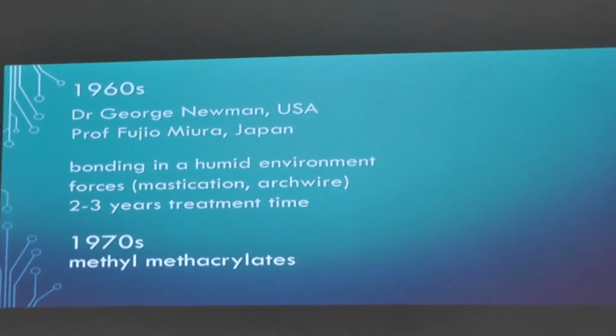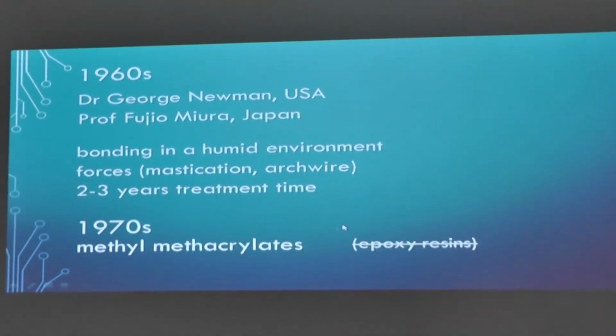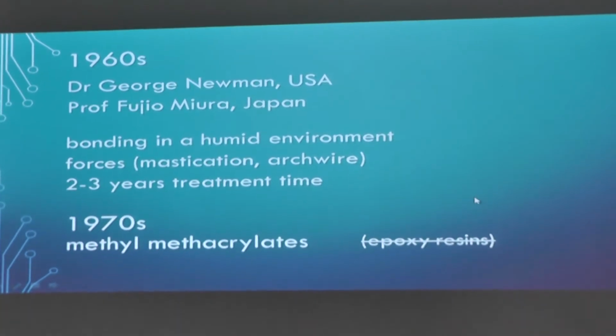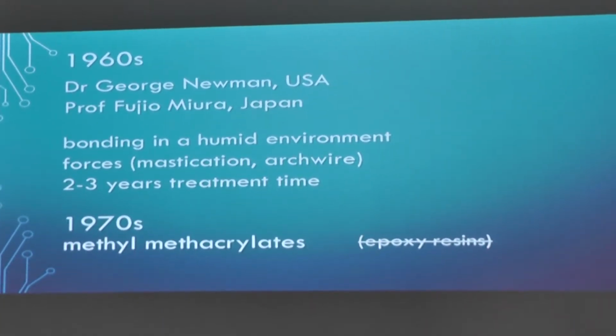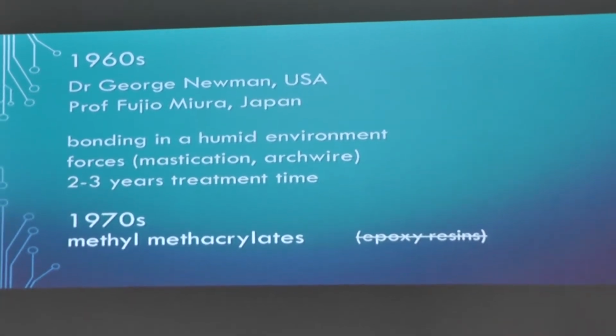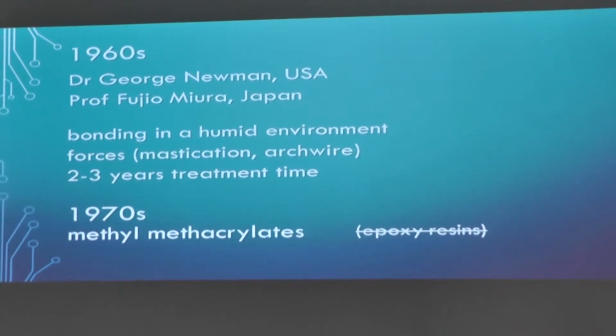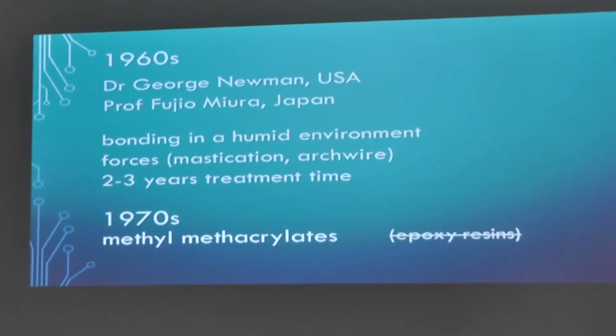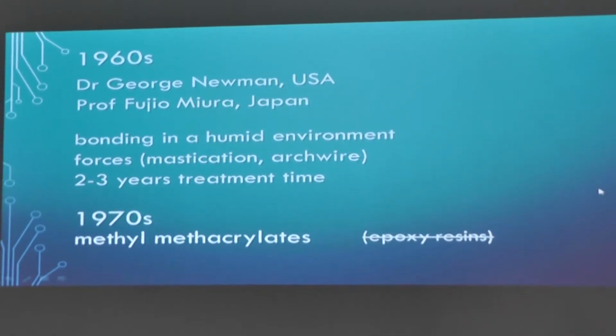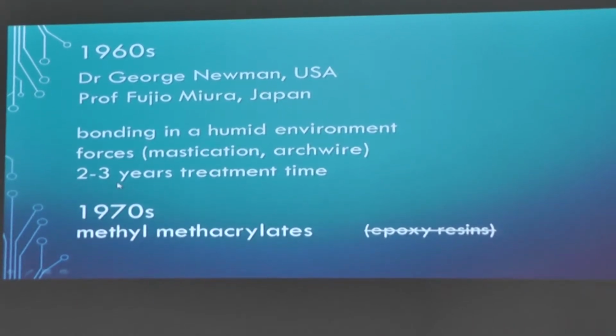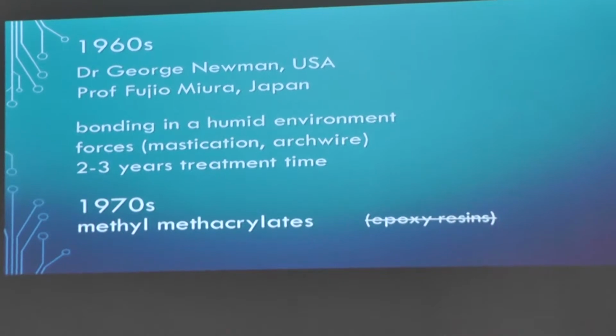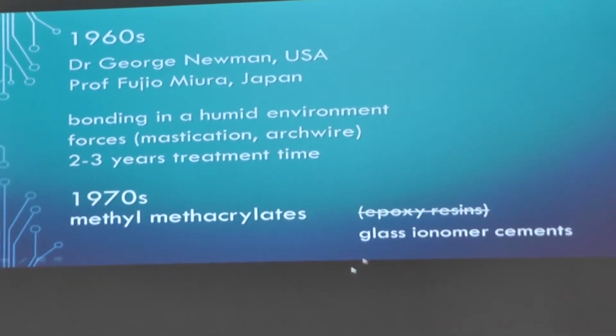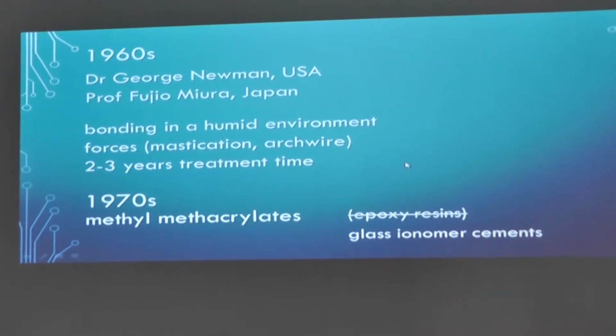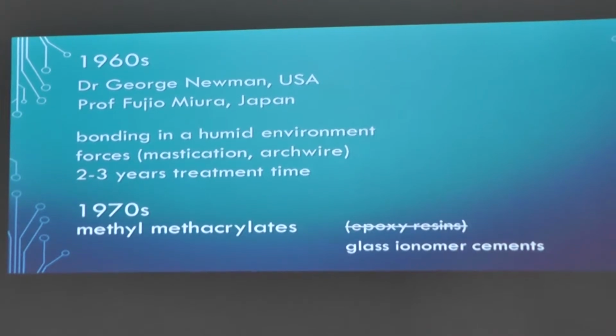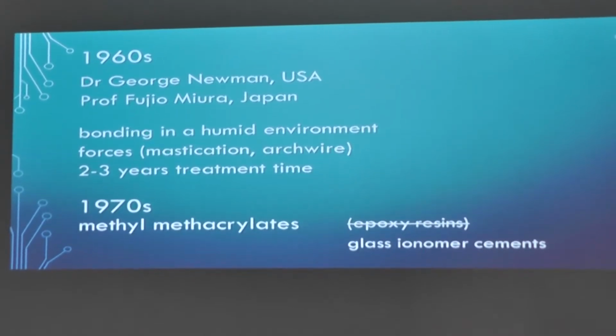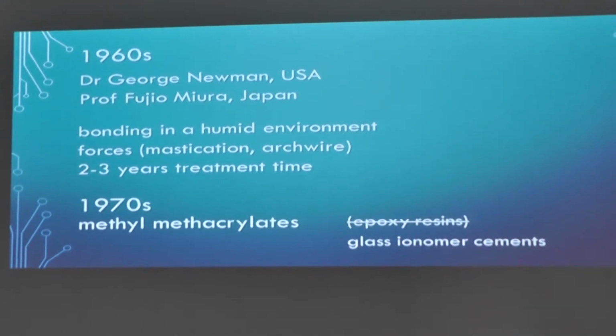materials were actually developed and used clinically. They consisted of methyl methacrylates, and also epoxy resins were experimented with, but they didn't have wide application because they have some toxicity, and they are very yellow always in color, which doesn't have to be a problem in orthodontics, but they weren't developed afterwards for cosmetic dentistry, and all these ones were developed on the basis of research for restorative and cosmetic dentistry. And also bonding was and could be performed still with glass ionomer cements that are superior in fluoride release than adhesives from methyl methacrylates, but they don't show high enough bond strength.